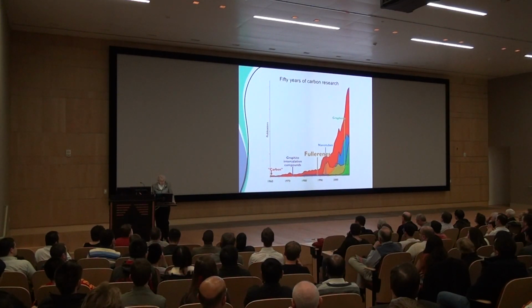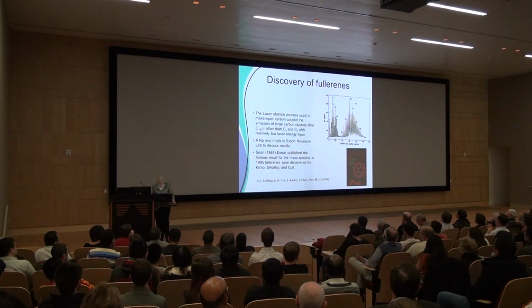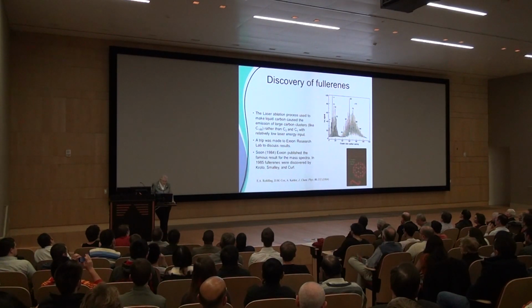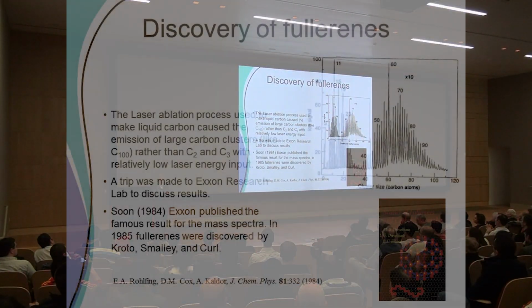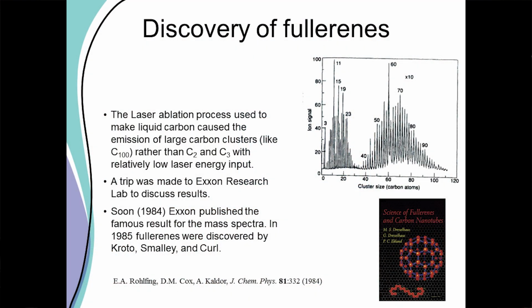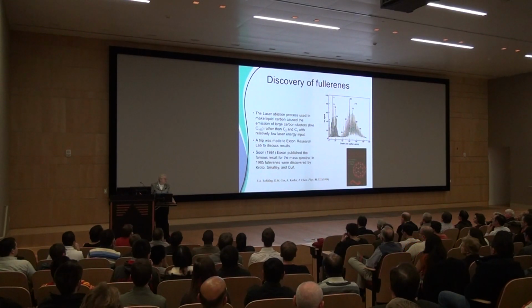So moving fast forward, now I'm moving into the 1980s. In this period, I had an idea and put a student to work. What happens if you have a surface and a laser comes in and hits the surface? We're going to put quite a bit of energy into the laser, so it does something to the surface. What it did is pull out little carbon clusters, and I expected it would be C2, C3, C4, like that. And it did exactly that if they weren't too energetic.